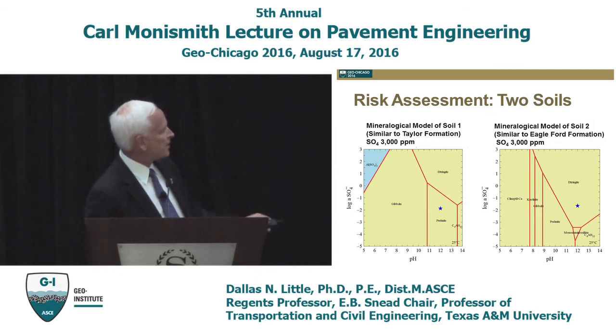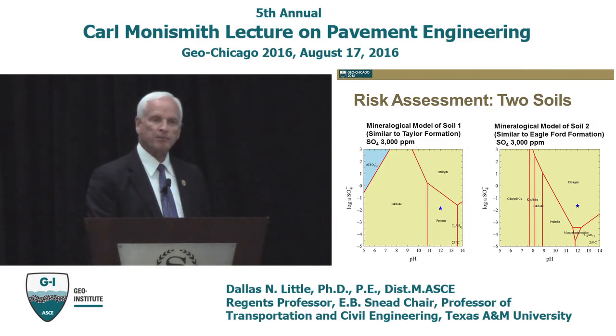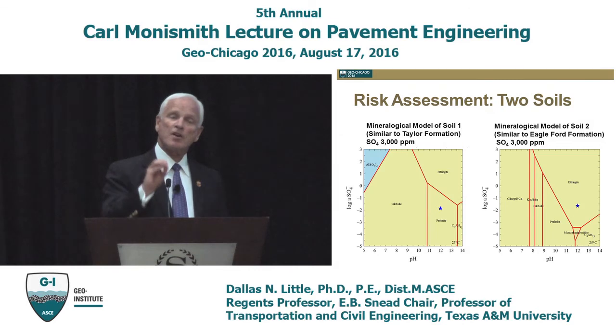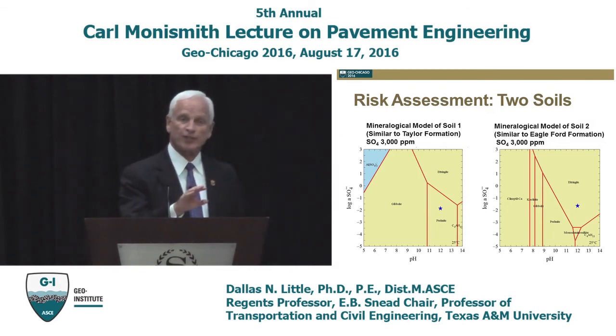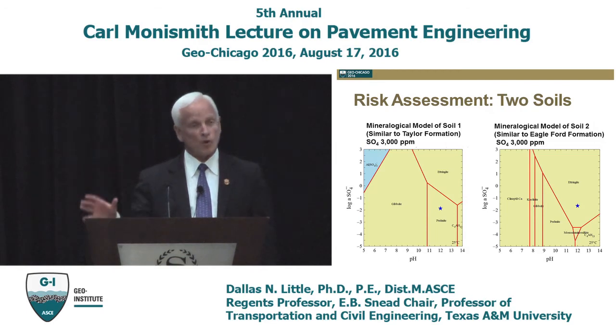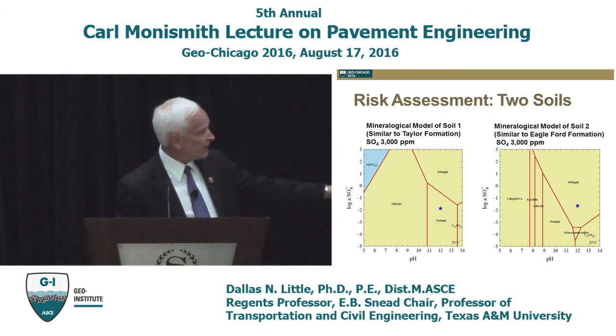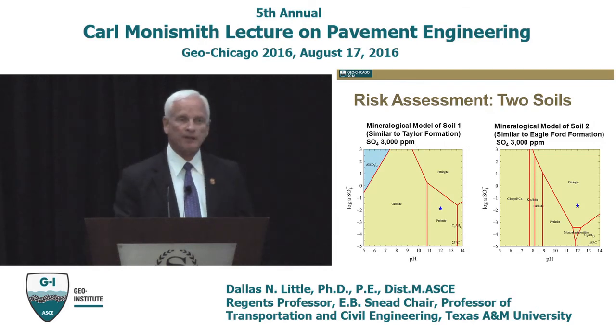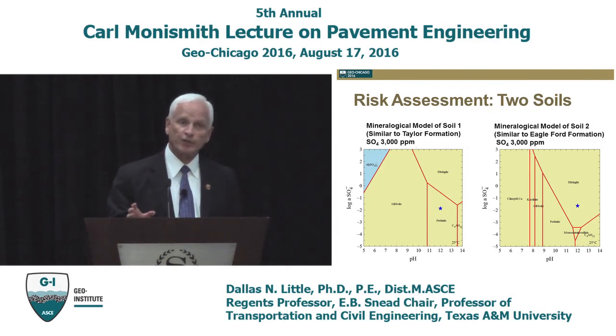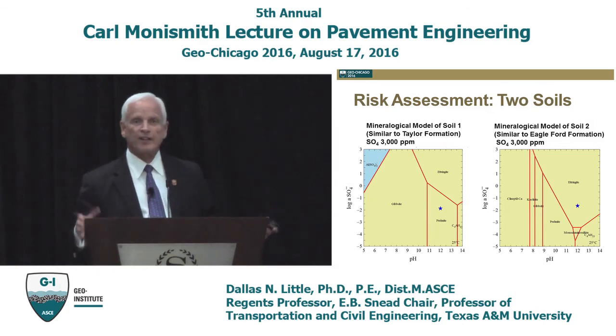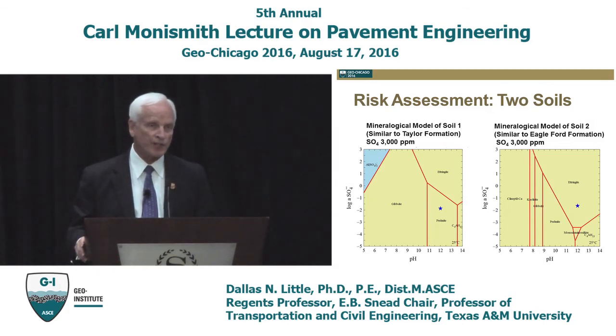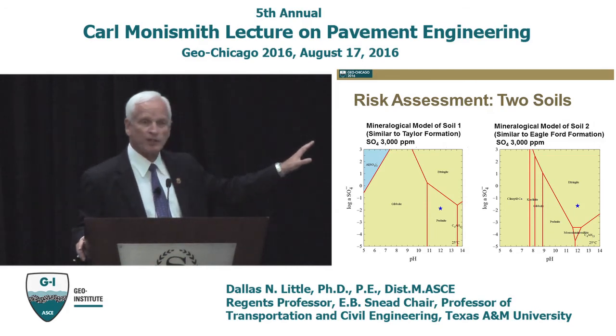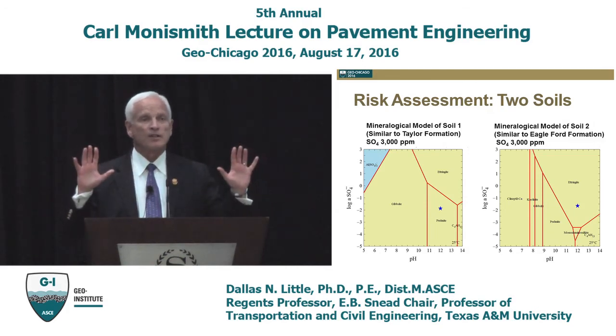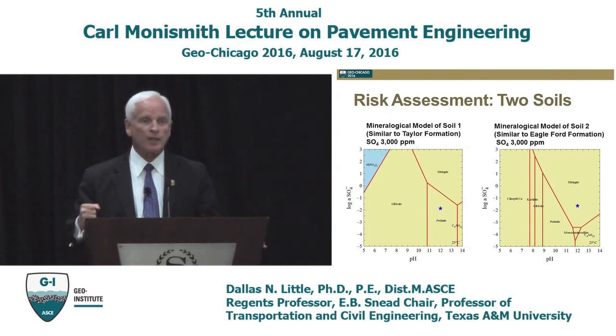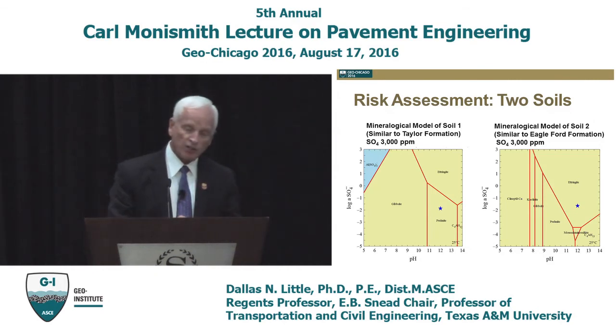So at 3,000 parts per million, if I'm in this soil mineral, I am outside of the ettringite polygon, which means that some other mineral has a lower free energy than ettringite, and that other mineral will form ultimately. If my star is within the ettringite polygon, then it tells me that ettringite has the lowest free energy. So that's one way to evaluate whether you're going to have the potential for ettringite formation, and I don't have time to go into that in any more detail, but it is a stability diagram, or a way to evaluate Gibbs free energy.